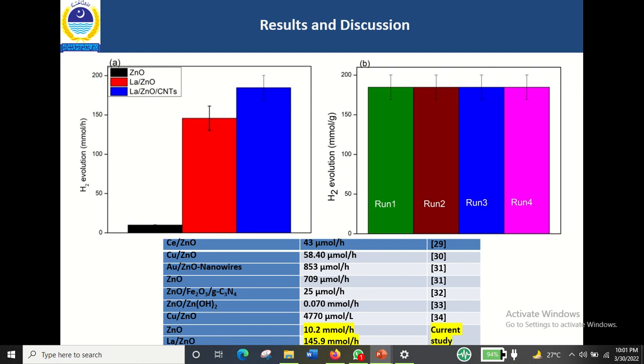So another factor which is important in using a photocatalyst for hydrogen evolution or environmental treatment is its recyclability or stability, because these two factors add to the economic value of the photocatalyst. So we repeated the 5 cycles with the same photocatalyst to check its stability over multiple cycles and its hydrogen evolution activity. If we see on the right side, there is no reduction in the photocatalytic activity of the composite photocatalyst over repeated cycles. In each cycle, it produces almost similar hydrogen evolution rate, which shows its high stability and recyclability under similar conditions.